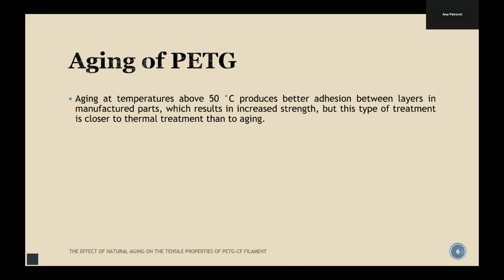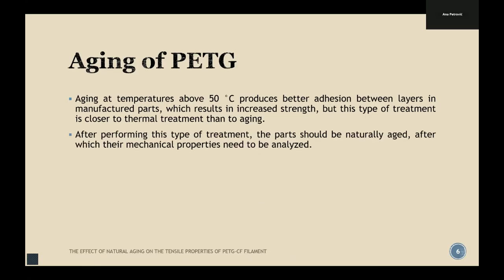Aging at temperatures above 50 degrees Celsius produces better adhesion between layers in manufactured parts, which results in increased strength. But this type of treatment is closer to thermal treatment than aging, so we will look at it as thermal treatment. After this type of treatment, the parts should be naturally aged, after which their mechanical properties need to be analyzed, so we can see after some period of time whether the parameters go down, increase, or what happens with the part.